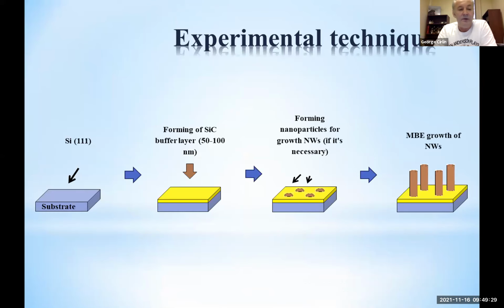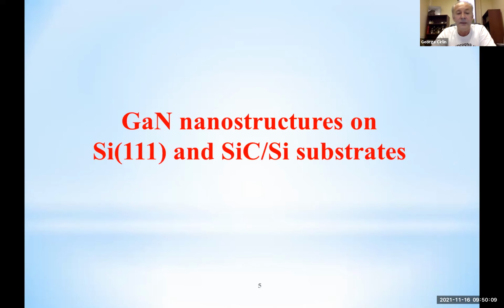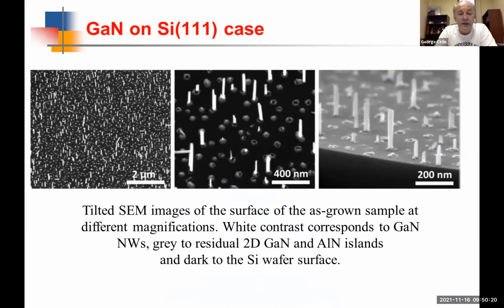For the growth of nanowires, we use different kinds of substrates. One of the typical ones is silicon 111. Another one which we use is the so-called hybrid silicon carbide on silicon substrates. And the growth proceeds in a very typical way. So we somehow create holes which penetrate to the substrate surface, and then if we open the shutters of the desired sources, we may start to grow the nanowires. The first story will be about the growth of gallium nitride nanostructures on this kind of substrates. This is the beginning of the story.